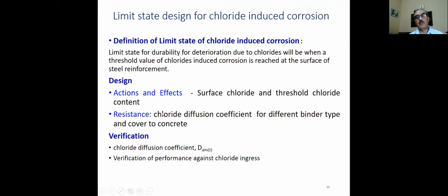Resistance is provided by chloride diffusion coefficient here for different binder types and cover of concrete. Earlier we had carbonation coefficient, here we have chloride diffusion coefficient. And verification, again we do verification of the chloride diffusion coefficient and then verification of performance against chloride ingress.